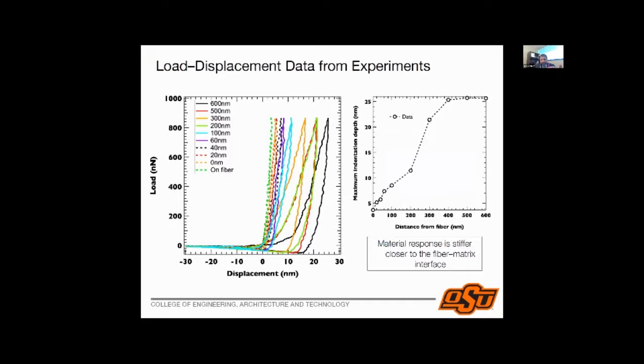If you look for elastic properties, when I follow the black line, suppose I have one path. I see that when you're loading and unloading, the path is different. So that means there is some plastic deformation when you go farther from the fiber. Yeah, this is a good point. The loading path here is different than the unloading path. That means you see some plastic deformation. That is why we use the unloading, because the unloading will be only elastic, right? So we use the unloading part to get elastic properties.